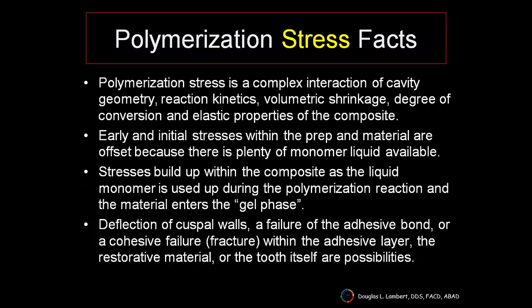Now, the stresses that happen when you turn the light on are very complex because it's an interaction of cavity geometry, reaction kinetics, volumetric shrinkage, the degree of conversion of the composite, and the elastic properties of the material itself. Early and initial stresses within the prep are offset because there's plenty of free monomer around. But as those covalent bonds start to form and they're used up, then during the polymerization reaction, the material starts to enter the gel phase. And as it goes to a polymerized state and gets hard, things can happen. Deflection of cuspal walls, a failure of the adhesive bond, a cohesive failure within the adhesive layer, the restorative material itself, or even the tooth are possibilities.